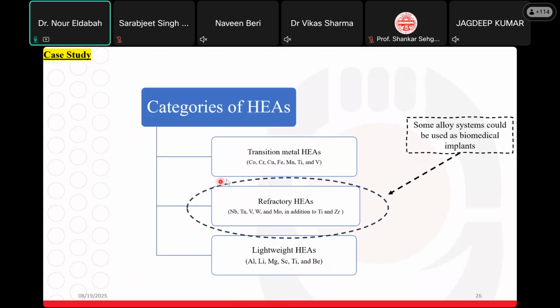If we look for the high entropy alloy and we try to pair between the biocompatibility elements and the refractory high entropy category, we can find most of the elements are biocompatible, excluding the vanadium and tungsten because of their toxic effect. We can find niobium, tantalum, titanium, and zirconium are all composition of the refractory high entropy alloy. So researchers have thought about this type of alloys as biomedical implant, so we can benefit from the biocompatibility of these elements and high yield strength of this category to be used as a biomedical implant.